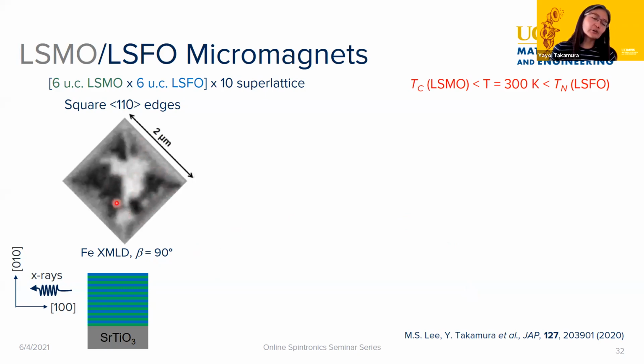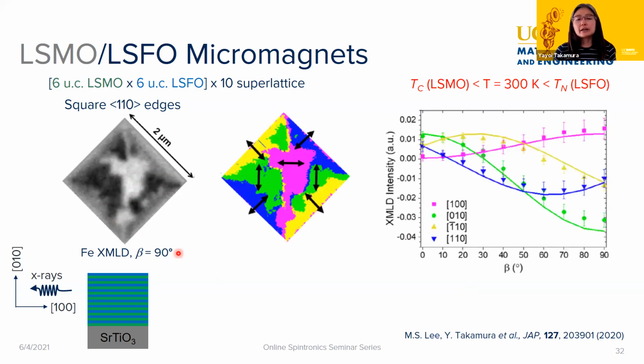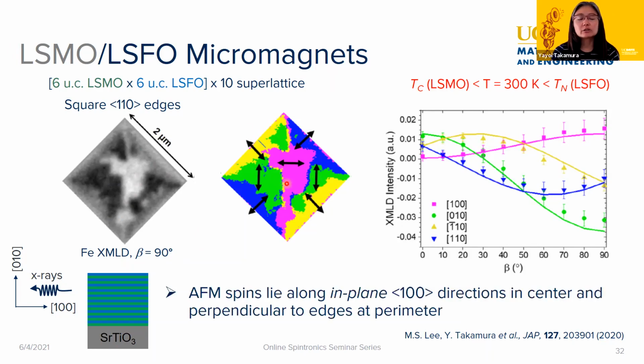And then the regions along the edge are sort of uniformly gray. Again, what we did is bin them, and now we get 4 different types of domains. In the center, we get our easy axes domains, which follow the same directions that we saw for the previous example, so just those green and pink domains. And then at the edges, there's a small region which we could bin as blue and yellow.